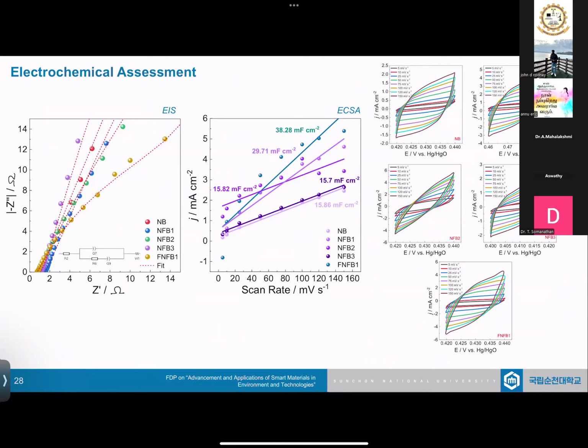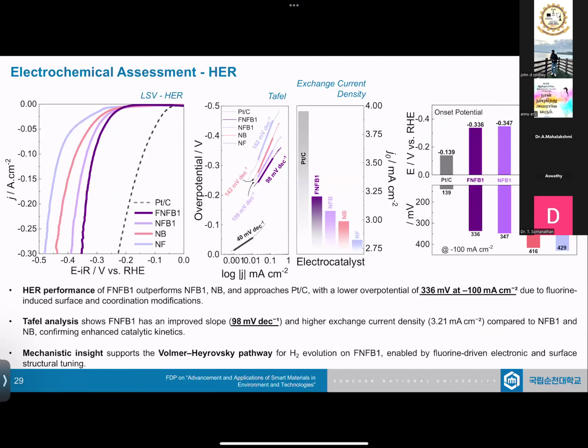The surface area is altered, as you can see, with respect to NFB1 and FNFB1, with fluorine and without fluorine. It has been completely changed, a substantial difference that is because of the inclusion of fluorine, not anything else. We did the electrochemical assessment with respect to the hydrogen evolution reaction.